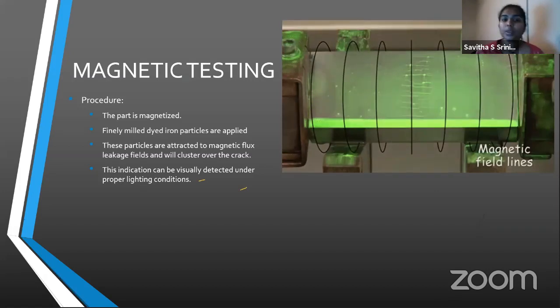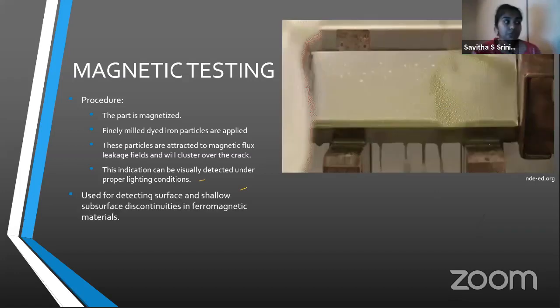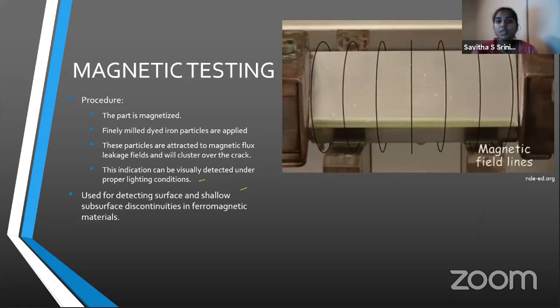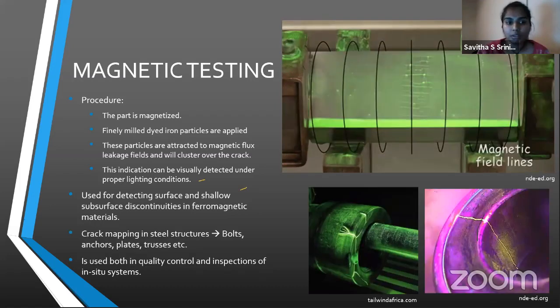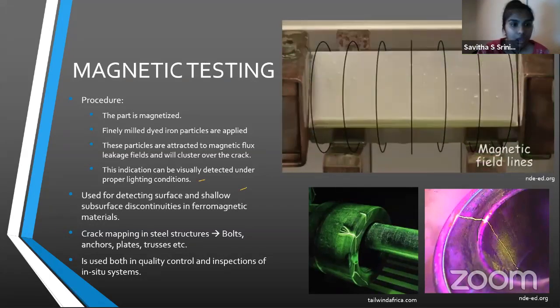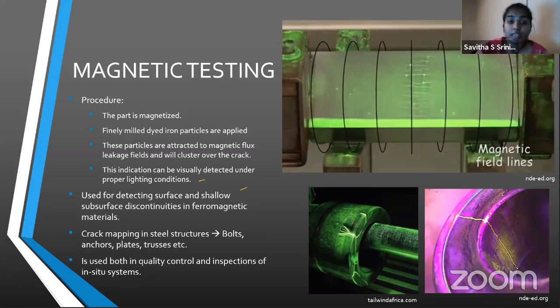This method is specific, and can be used only for ferromagnetic materials such as iron, nickel, cobalt, and some of their alloys. And it can also be used only to detect surface or very shallow subsurface cracks in iron kind of materials. It's typically used in crack mapping of steel structures like bolts, anchors, plates, trusses, etc. Again, it's used in both quality control as well as for inspection of in-situ systems. So you can essentially test a bolt or a plate and then send it in service because this is an NDE test.